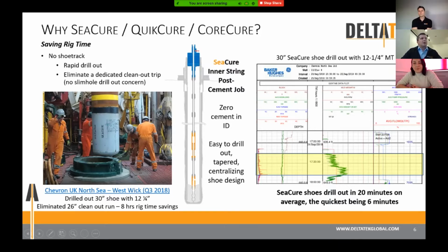And this is primarily brought through eliminating the shoe track in the most efficient form of a SeaCure job. The biggest value statement around eliminating a shoe track is eliminating a corresponding dedicated cleanout trip. This is especially relevant for a bigger step down in size, like with the slim hole well design. As you can see in this case study, which we'll review in detail, for Chevron in the UK North Sea, they drilled out a 30-inch shoe with a 12.25-inch assembly, which prior to using SeaCure required a 26-inch cleanout run. So we saved a minimum of 8 hours of rig time there.